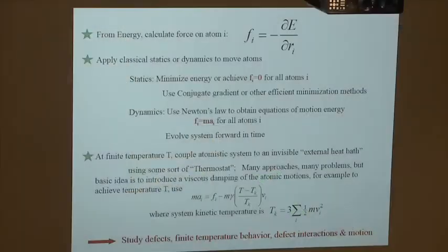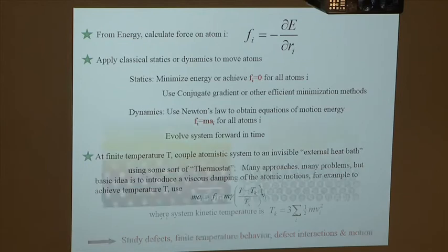But if you do things properly, then you can study collections of atoms that form defects, vacancies, grain boundaries, cracks, dislocations. You can study them at finite temperature. You can apply loads and watch the defects move. You can see how the defects interact. And so this gives a lot of insight into what the fundamental defects in the material are doing.